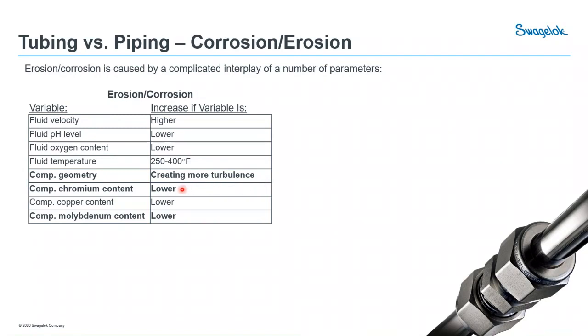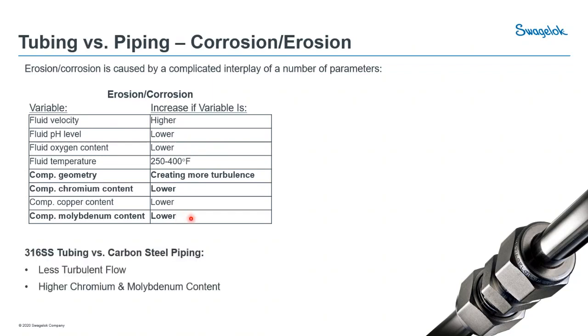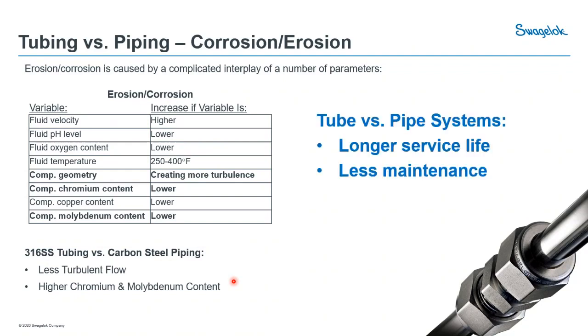And again, here, if you have lower chromium and lower molybdenum, that's going to increase the erosion and result in more corrosion. So again, if we look at the typical comparison, if we're looking at 316 tubing, which is most commonly used, versus your traditional carbon steel piping, you have that less turbulent flow, and naturally you have higher chromium and higher molybdenum content. So overall, if we look at tubing versus traditional piping systems, you're going to achieve a longer service life and really less maintenance. So a lot of the cost savings and the performance you're going to achieve over that longer life, less maintenance, and really just have a better performing system.